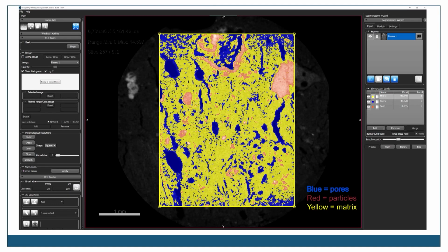So I'm using Dragonfly to study pore systems in micro-CT images of samples taken from these small sherds. It's an advantage that we can do a micro-CT scan and then also make a thin section or do other analytical methods on the exact same sample. Since I have limited expertise in deep learning, I use the segmentation wizard, which, as Franklin mentioned, I think makes this an easy process. And I generally only need about 3 slices to get a good model for training on.